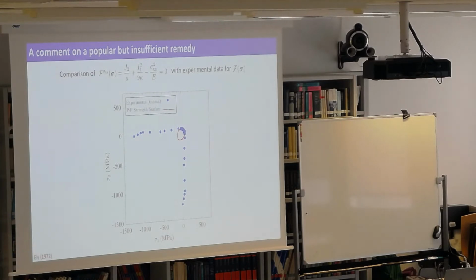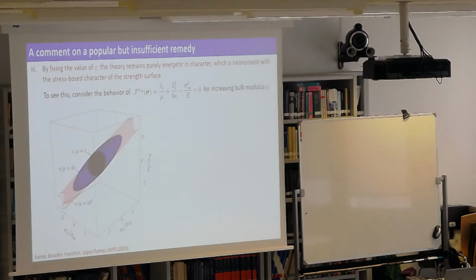That the equations are general, right? That somehow you have nucleation in the equations if you put it, right? This is just one calibration. But okay, what if you do a different calibration, right? So this is actually how we realized that maybe we need to deal with this in a different way. So even though it's 3D, it's really the first thing that we ran because we were dealing with elastomers. So elastomers are incompressible. So if you look at what happens when you use this theory in the first quadrant, so this is the strength surface by calibrating things with the uniaxial tension.